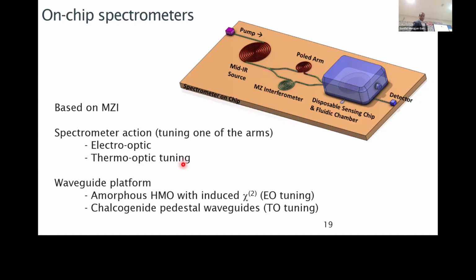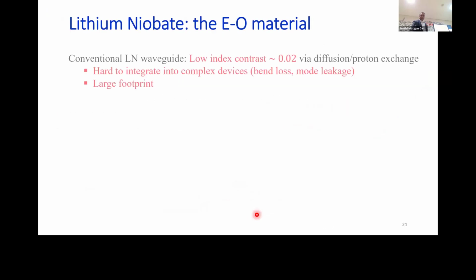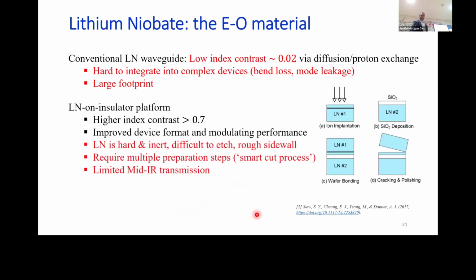The first platform is based on induced Chi2 nonlinearity, which is nothing but the electro-optic effect. The second platform is based on chalcogenide waveguides, which, when applied with temperature, change the refractive index. Let me quickly show you some details about the electro-optic platform, where the best material for electro-optic activity is lithium niobate.